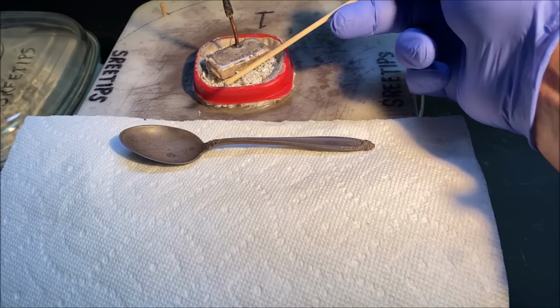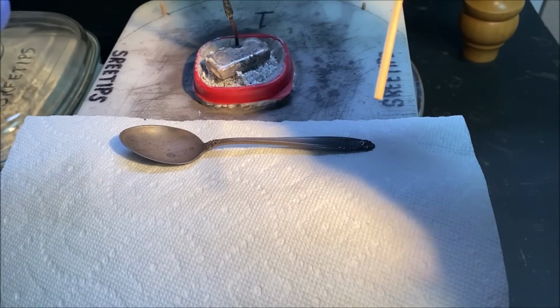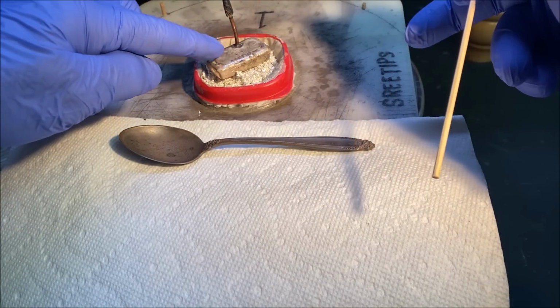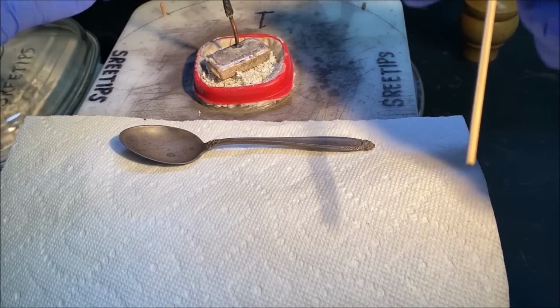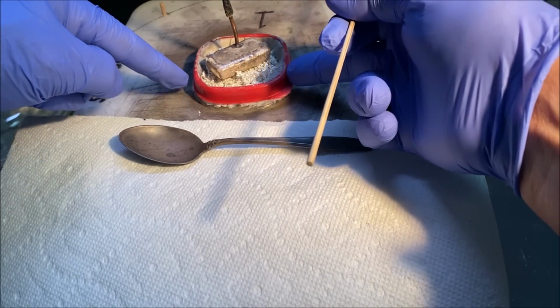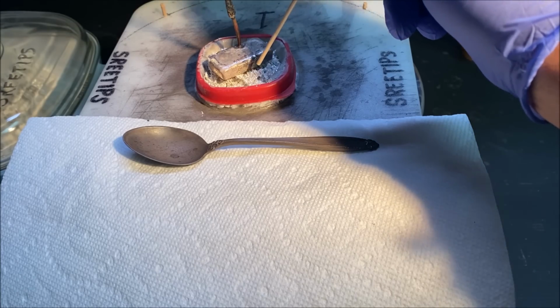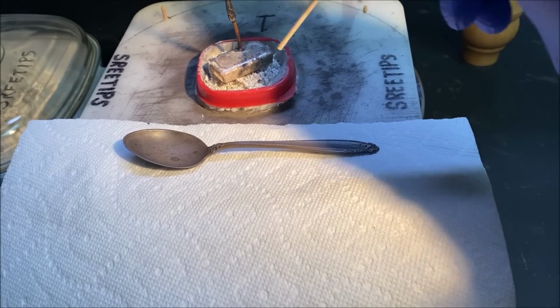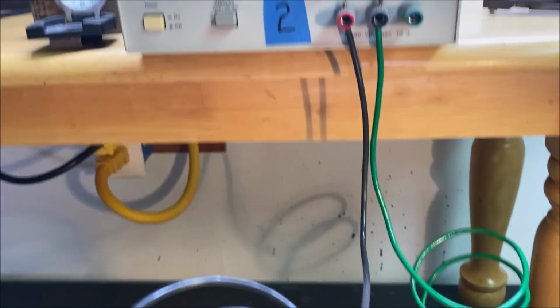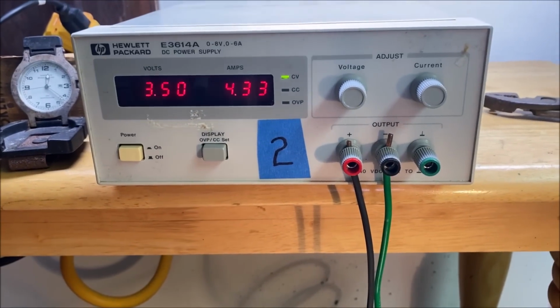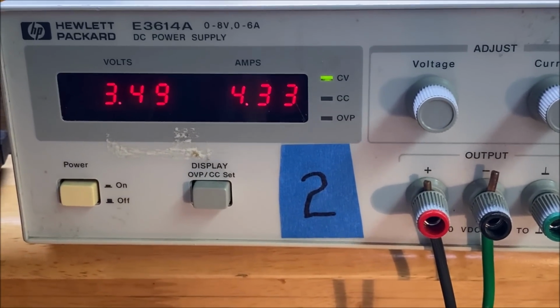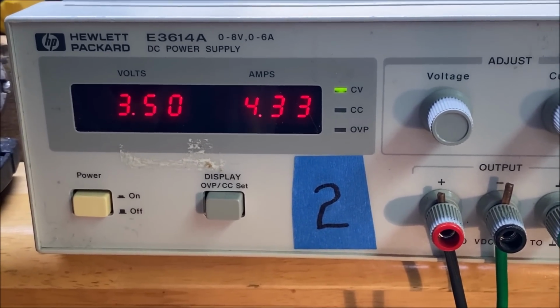When I came in, the silver level was full, like it is right now, and I hit it with this bamboo skewer, and it just collapsed. And the electrode bar fell down into the filter. When I hit that, the silver collapsed, reestablished the contact, and look what amps are now. It just jumped up to over 4 amps.